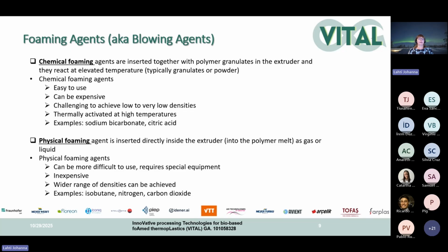Both of these agents have pros and cons. Chemical foaming agents are typically easy to use, but they can be quite expensive if we compare to physical foaming agents. And then there can be some challenges to achieve the low or very low densities. And you can see some examples like sodium bicarbonate or citric acid that can be used as chemical foaming agents.